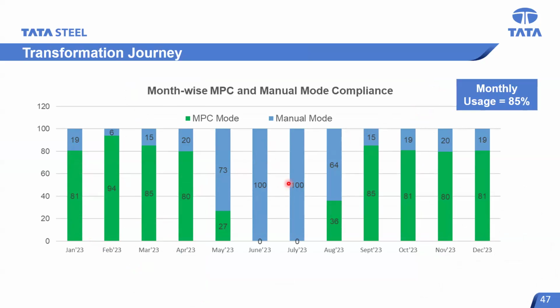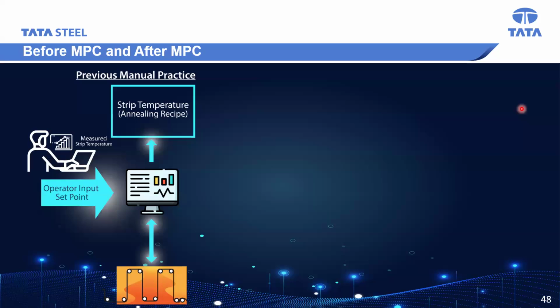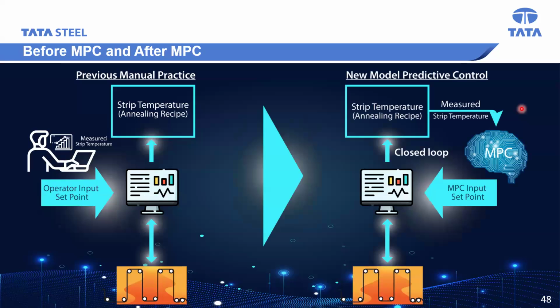You will see here that for these two months there was a line shutdown for some major revamp, so that is why you don't see usage here. Otherwise, on average, it is used 85%, and in some months it goes up to 95%. This shows how the operator previously used to give the set points; now the MPC solution is giving the set points. So it's a closed loop control. There is no open loop here.